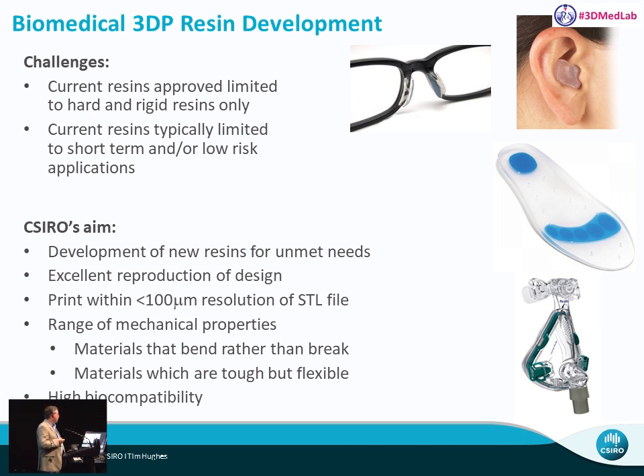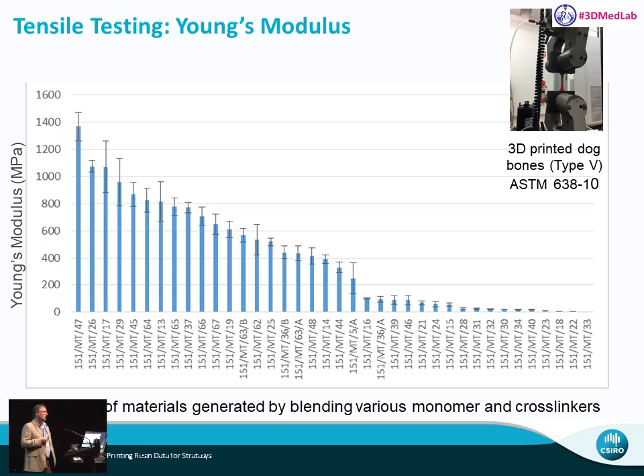So the way we went about this was making libraries of materials. We'd mix up different ratios of monomers and crosslinkers and additives, and we'd measure the outcome, and then we'd build up a structure-property relationship. And from this, we were able to then make a library of materials with a broad range of mechanical properties. And this is measuring the mechanical properties by Instron in tensile testing.